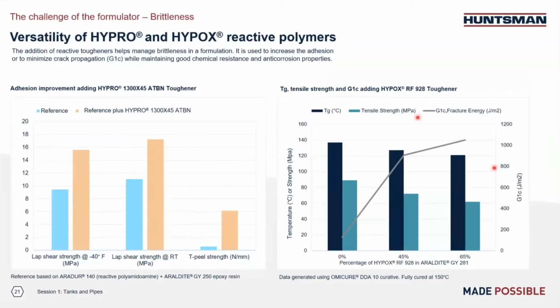On the right side, we're adding HYPOX RF928 into the epoxy resin side. By introducing toughener into the epoxy domain, we improve the overall system mechanical properties. Here we measure the TG and the G1C. In the reference, without any toughener, you can see the system TG is about 137 degrees C, but the G1C is only about 200. G1C is basically the energy needed to cause the crack, right? If we introduce the toughener to the system at 45%, you can see we can increase the G1C all the way to almost 900. That's almost a 5 times improvement, which means you now need 5 times more energy to cause the crack, right?